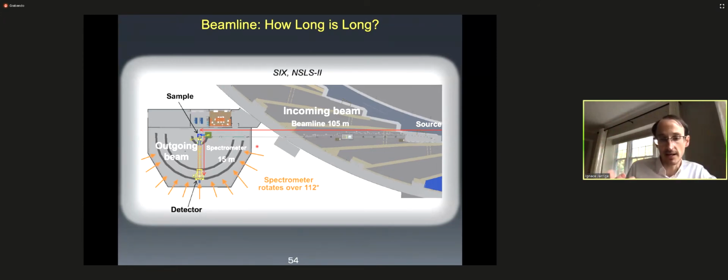So you measure the energy loss here because you have a grating that monochromatizes the rays scattered off the sample. You're going to have the whole spectrum basically projected on your detector, because the grating will break down all the different wavelengths and project them onto the detector. That's your energy axis here on the detector. But if you want to measure the momentum transfer to look at the dispersion of an excitation, like a spin excitation or lattice excitation, you're going to have to rotate the spectrometer about the sample vertical axis. That's how you do it here, on the rails.